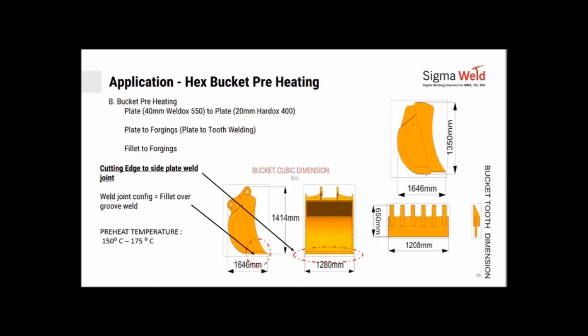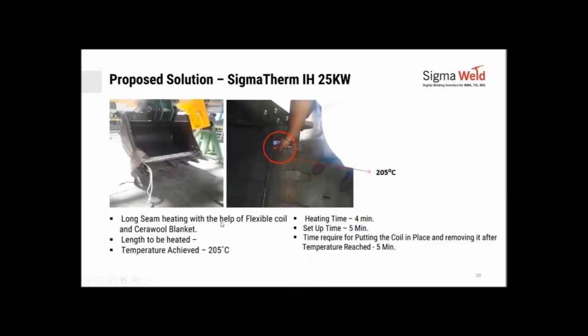Again, if you look at the Hex bucket, it's got about a 20 mm thick to a 40 mm thick plate that needs to be welded here. The tooth that goes on each side is about 60 mm thick. Materials are Weldox and Hardox here. And the challenge is to preheat them above 205 degrees. The way to do it with induction, we place the coil here, a simple ceramic blanket below it, and you could achieve 205 degrees in under 5 minutes.